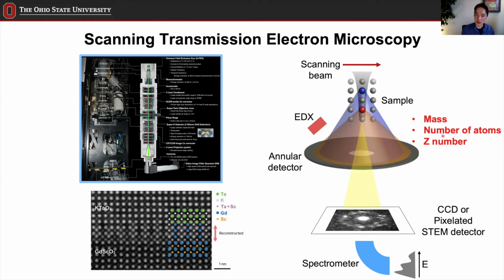Okay, so that's the primary method that we use to determine the structure, and also to get some chemistry information. This is one example that I'm showing here, which is potassium tantalate grown on gadolinium scandate. We are looking at the interface. That's the film growth direction. As you can see, we can resolve all the atoms, even smaller ones such as potassium. And then something's happening at the interface. What we figured out in this case was that the structure gets reconstructed right at